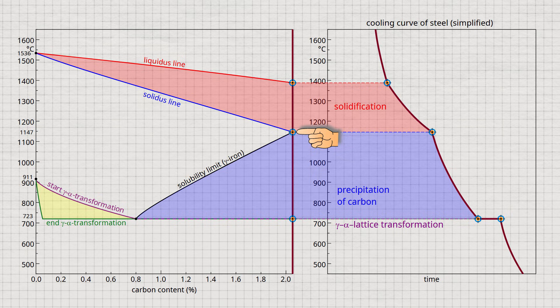So in this case carbon is precipitated from the microstructure immediately after solidification. This maximum solubility of 2.06% carbon in the face-centered cubic lattice structure of gamma-iron represents the maximum carbon concentration that a steel can take up. This is why iron materials are called steels up to this limit. Higher carbon concentrations result in a fundamentally different microstructure.